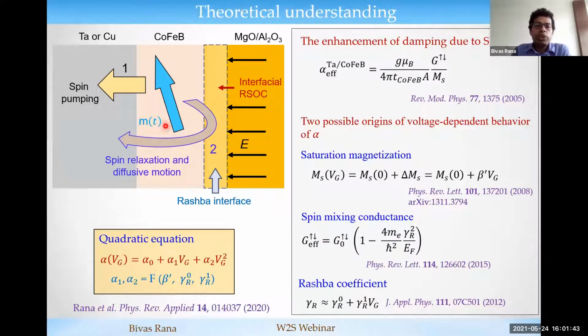Now, about why this nonlinear behavior is occurring. As you know, when we excite the ferromagnetic resonance in a ferromagnetic thin film, it pumps pure spin current into the heavy metal. So that is the major source of losing the spin angular momentum, and hence damping. The enhancement of damping can be expressed by this, where G up-down is the spin mixing conductance. In general, this spin mixing conductance is not affected by the gate voltage applied at this interface, because it is an interfacial property of the system.